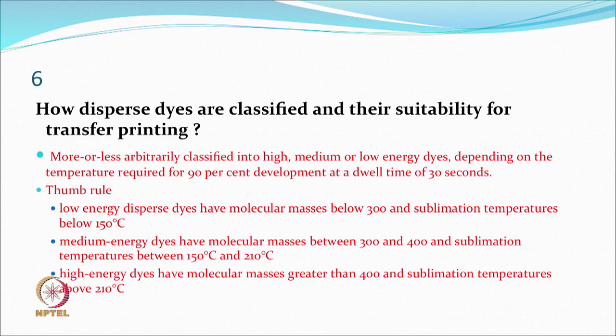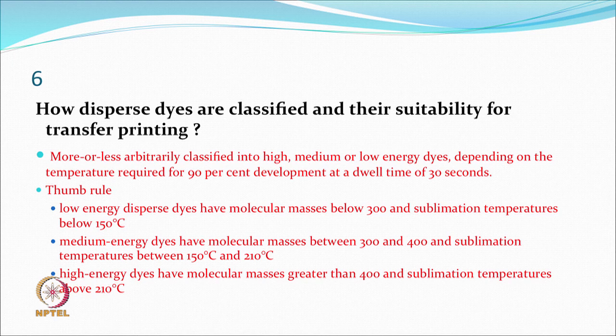As a general thumb rule: molecular weight may be less than 300 for low energy dispersed dyes, and sublimation temperatures may be below 150°C. Medium energy dyes have molecular masses between 300 to 400 and sublimation temperatures between 150 to 210°C — this is a very large range. High energy dyes have molecular weight more than 400 and sublimation temperature also more than 210°C, requiring higher transfer temperatures.